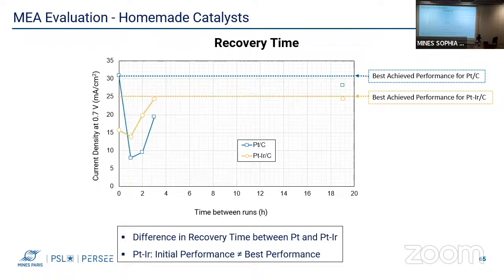This means that there could be not only a problem of turnover, but also a problem of mass transport limitations inside the catalyst pores. It is also interesting to see that the best achieved performance for platinum-iridium on carbon is not the same as the initial performance. This could be related to the fact that iridium could be oxidizing into an activated oxidation state as the electrolysis takes place. This hypothesis, however, needs to be validated.